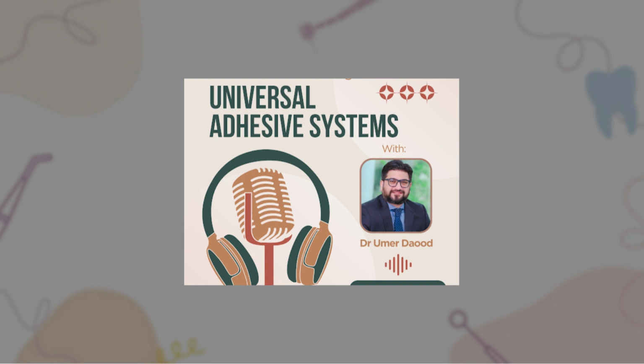We know that, right? It is equally clear that it is possible to prevent or at least significantly slow down the rapid hybrid layer degradation, because the degradation is going to happen anyway. So we've got to reduce that. The carious dentin is not necessarily an ideal substrate for strong and durable hybrid layer formation, so obviously you're going to avoid that. You've got to make sure that the soft infected caries dentin is removed and we've got more hard, glassy, or perhaps affected dentine there.